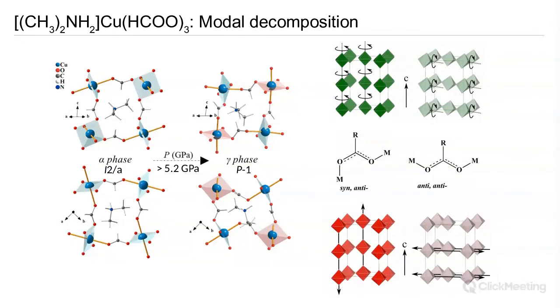However, if we introduce these unconventional rotations of the octahedra, then that's going to push the formate towards a syn-anti type bonding configuration. So if we work under the hypothesis that for some reason the formate wants to bond anti-anti, and it costs energy to be syn-anti, then we can understand the nature of the energetic competition leading to this phase transition. That is to say that the steric contraction of the lattice and the volume contraction from high pressure wants to create these unconventional rotations.